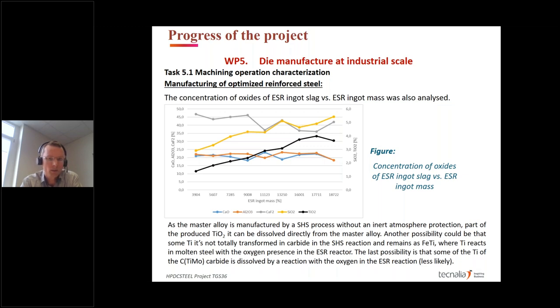the whole master alloy was finally added to the liquid steel pool. So there have been some reactions with titanium, either based on ferrotitanium, or it was not bonded titanium with carbon. So titanium did react with the oxygen present at our ESR plant, and we formed titanium oxides. But the rest of the master alloy has been